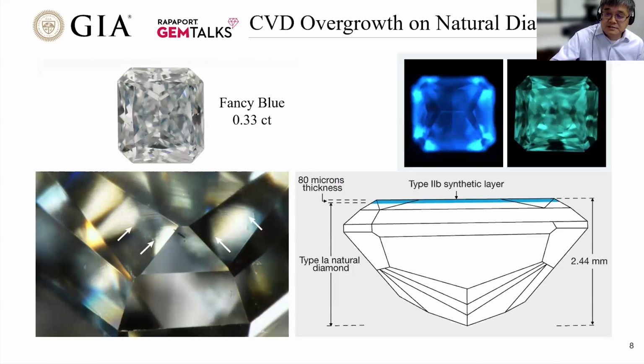The CVD technology can also be applied to a natural diamond seed. Here's a kind of extreme, very dramatic case. It is a layer of blue CVD diamond, only about 80 micron thickness, doped with boron. It's similar to natural type IIb diamond. It's doped with boron, overgrown over the table of a natural type Ia diamond as a seed. It turned the stone to a fancy blue color.